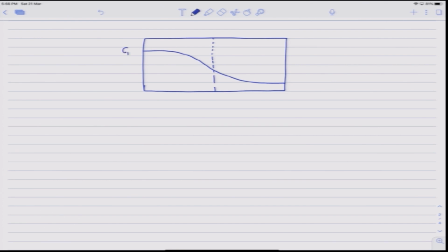So left terminal alloy concentration is C1 minus, right terminal alloy concentration is C1 plus, and suppose we placed some inert markers at the initial interface before the diffusion started, and after the diffusion annealing for time t, let us say the markers have shifted to position xk. This is the Matano plane position x naught here, which is the initial contact plane.